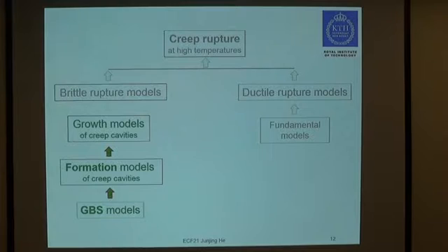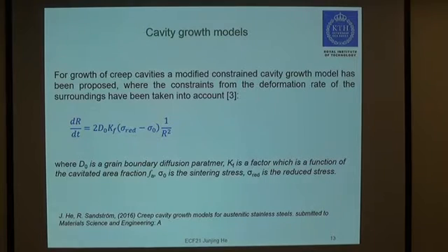Now we can go on with the cavity growth model. For growth of creep cavities, a modified constraint cavity growth model has been proposed, where the constraints from the deformation rate of the surroundings have been taken into account.